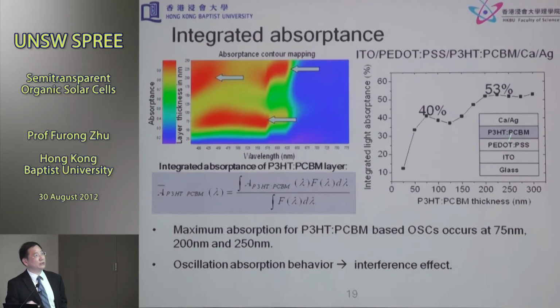It's a conventional cell where you have a very thick layer of reflective cathode. So what we do is that we calculate what we call the integrated absorbance. That means the light being absorbed by the active layer in an organic solar cell as a function of its thickness.